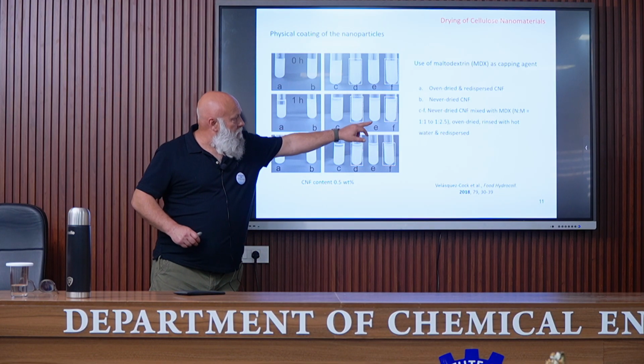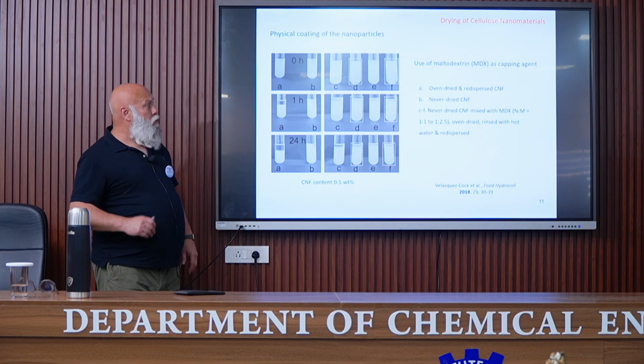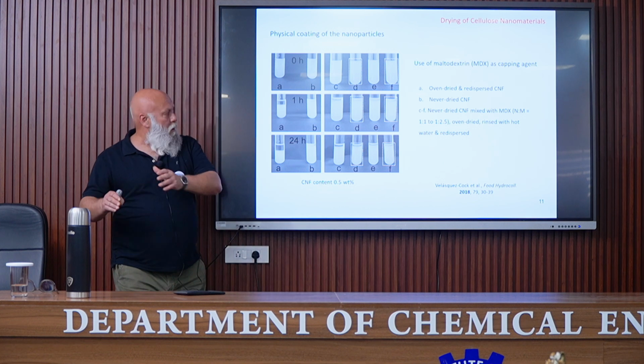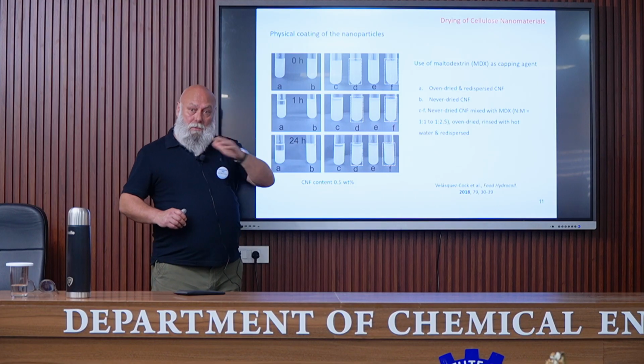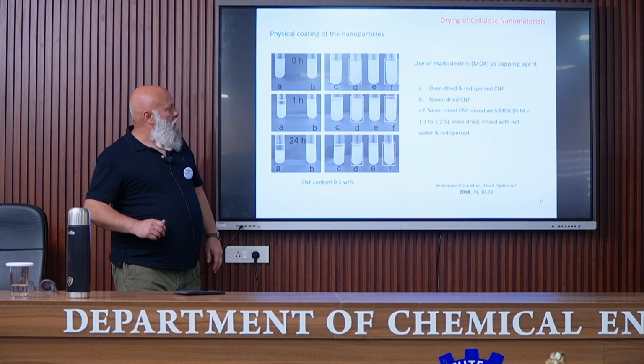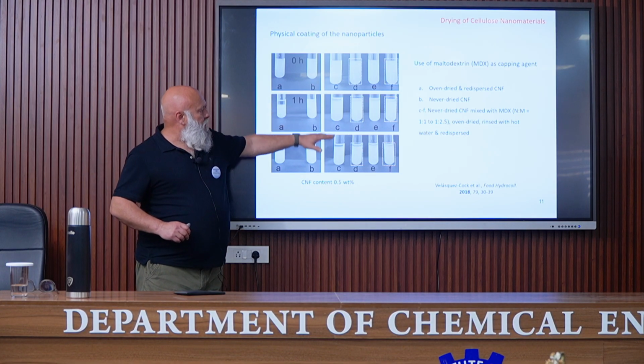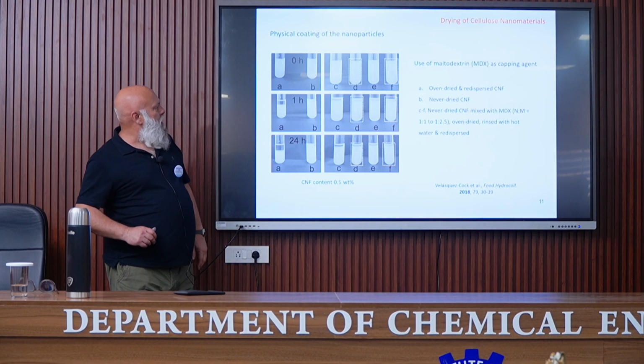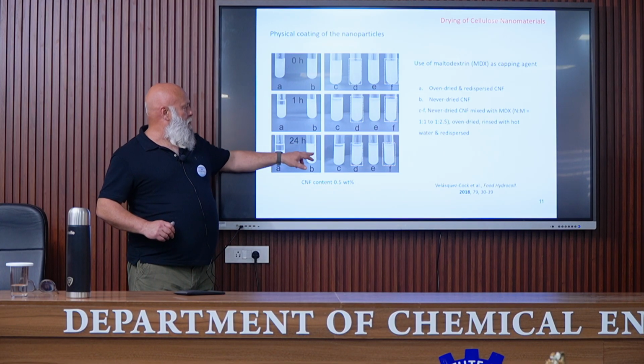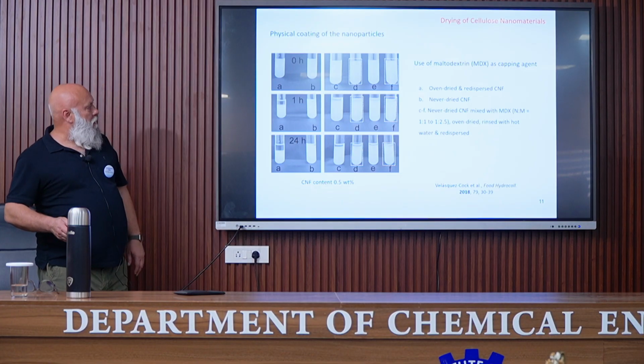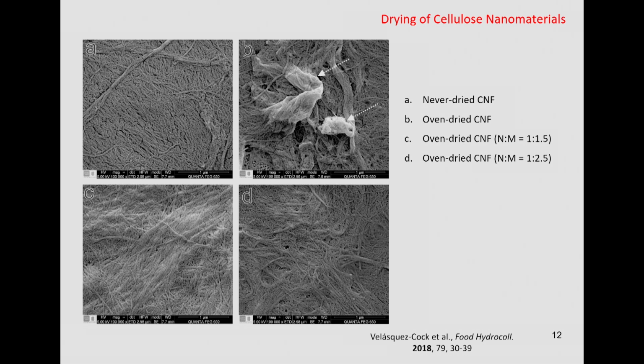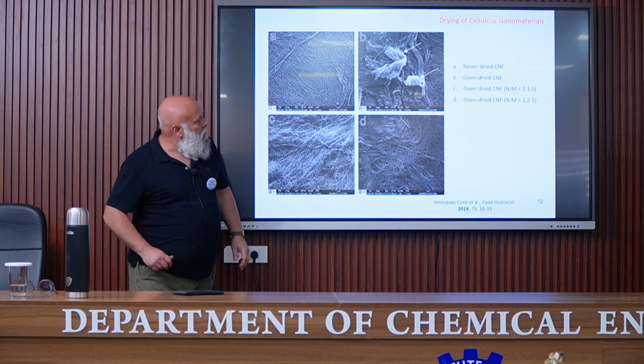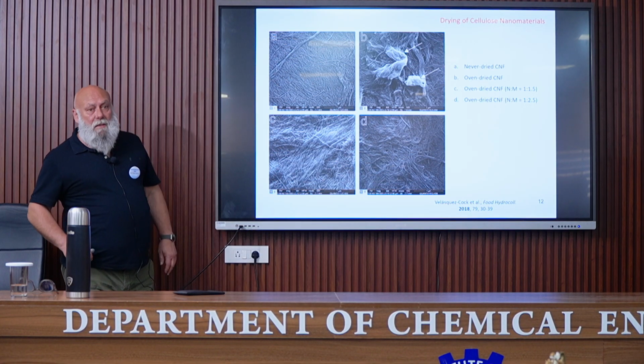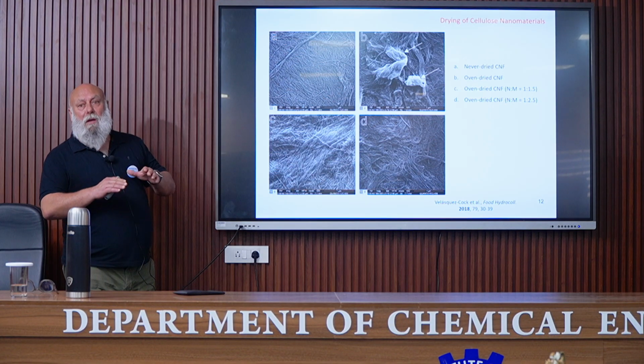And here you have dispersions that have been obtained from never dry CNFs that have been mixed with maltodextrin in different ratios, dried, and then rinsed to remove the maltodextrin, and it is rinsed with hot water and then redispersed. You can see that the stability is not so good as the never dry dispersion of nanofibrils, but much better than without maltodextrin. You can see here the aspect of these nanofibrils. Never dry cellulose nanofibrils, so we have these very thin nanofibrils. Oven dry cellulose nanofibrils, aggregates. And here, two nanofibrils that have been oven dried, but with maltodextrin that limits the aggregation of the nanofibrils.